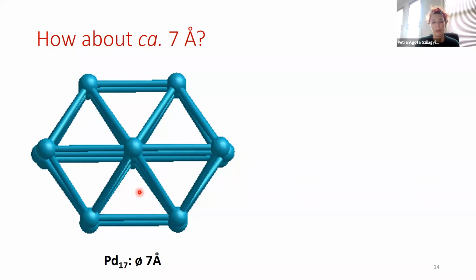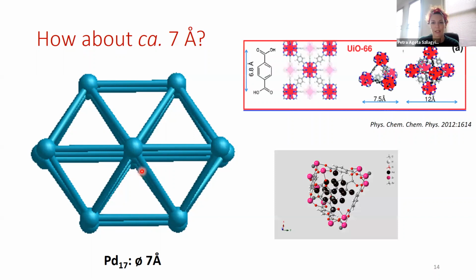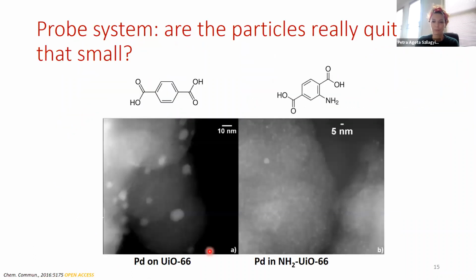So basically we have no interstices here. So as long as we produce this, in theory, we should produce no interstitial hydride. And it's just a little reminder that this is the topology of framework we opted for, because we knew that this has this 7.5 angstrom sized pore, which would be perfect to embed this kind of particle.